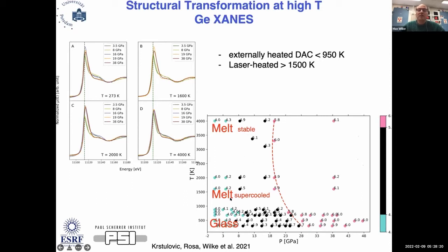But if we then go to the melt, either in the really stable region at very high temperatures or in this region where we would also expect to have some crystallization, but in the spectra shown here we have ruled out crystallization, we see that there's a shift of the conversion pressure to lower pressures, roughly by 30%. So we would expect that the conversion pressure that we determine in glasses should overestimate the conversion pressure that we really would see at conditions of the deep Earth.